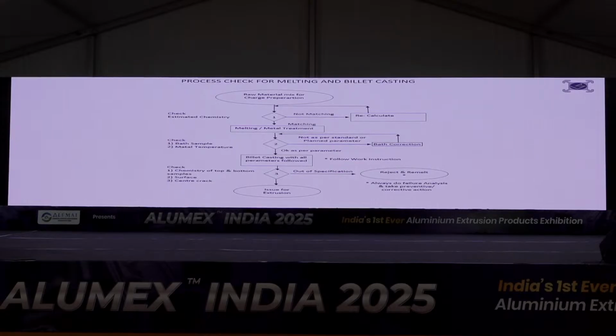You control your temperature. We control our temperature. That's the most important point. Not only will it reduce your melting loss, but it will give much better billet quality and billet casting stability. Never allow your temperature to reach beyond a permissible limit.